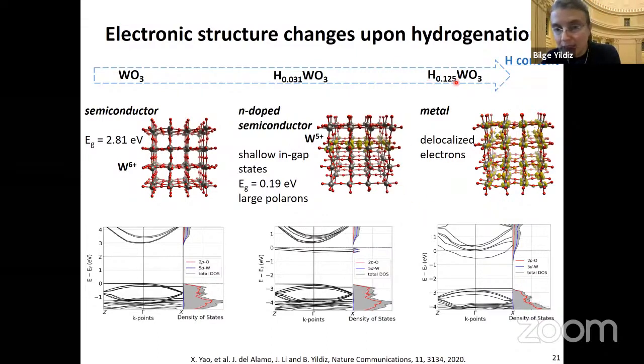And if we increase the hydrogen content above 10%, this delocalizes the electrons and the material becomes metallic, and the structure also becomes more symmetric, consistent with the experiments I have shown to you on the previous slide. So the N-type doping and the symmetry increase that transitions to metallic is what we see from our simulations, which is consistent with the spectroscopy and diffraction measurements.